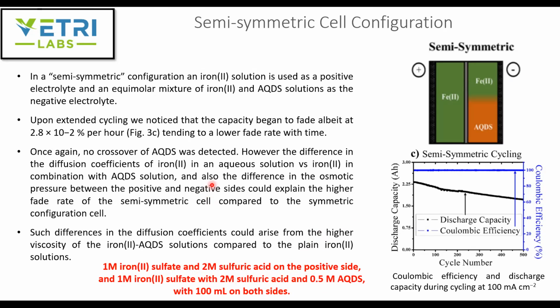100 ml volume. So when they recorded the discharge capacity, and here they did the cycling at 100 milliampere per centimeter square, which is different than the previous two studies. What they found out was that the capacity fade was about 2.8 times 10 to the power minus 2% per hour. So there is a lower fade with respect to time. Also, they did not detect any crossover of AQDS.